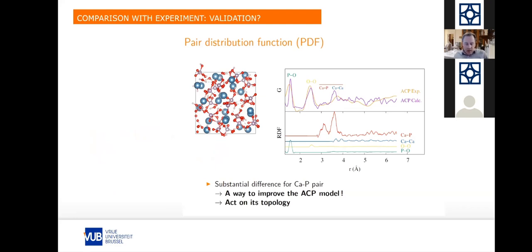the X-ray diffraction technique, or others, you can do electrons, neutrons, we can obtain pair distribution functions. What is this? This is the distance between two atoms. For example, here you see PO, so this is the distance of PO, phosphorus-oxygen, and we see how many times this occurs. We see different peaks arising, which correspond to different pairs of atom-atom distances. And this profile is a fingerprint of the amorphous structure.